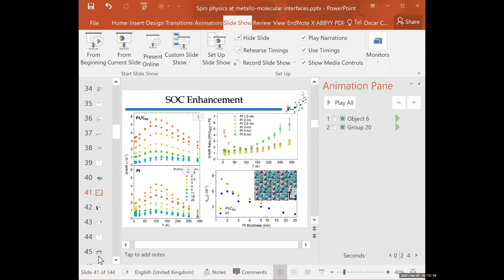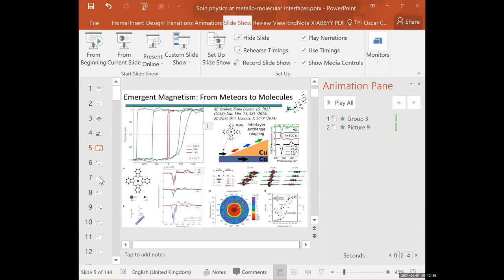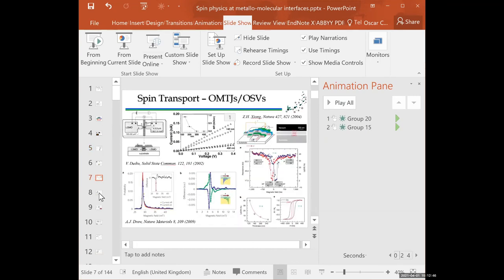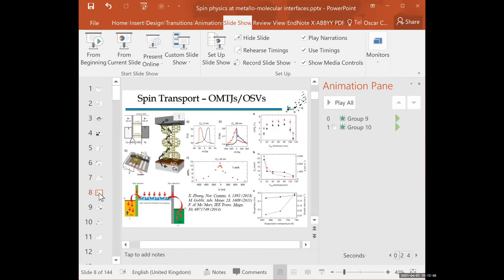Oscar, very nice talk, and you have summarized most of the work people have done. I have a question regarding the tunnel spin valve structure. What's the main mechanism in organic spin valve structures? Because there are three mechanisms: elastic tunneling, resonant tunneling, and so on. But here people are using thicker ones, and the spin diffusion length also varies from a few nanometers, 5 nanometers, to 100 nanometers. So what is the basic mechanism in such a spin valve structure?